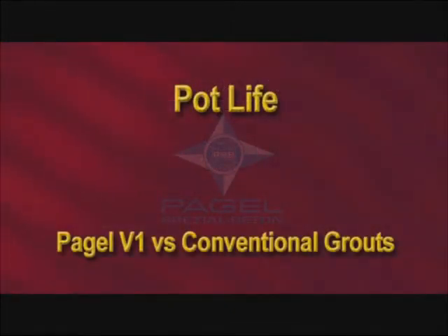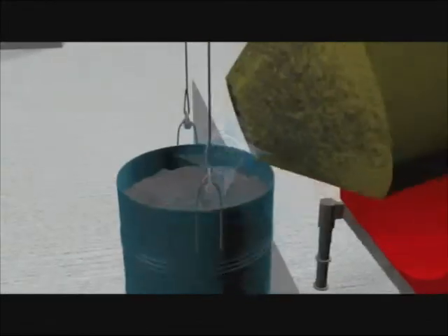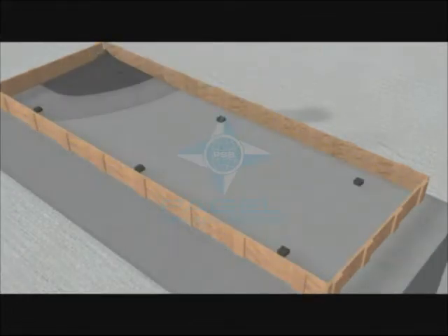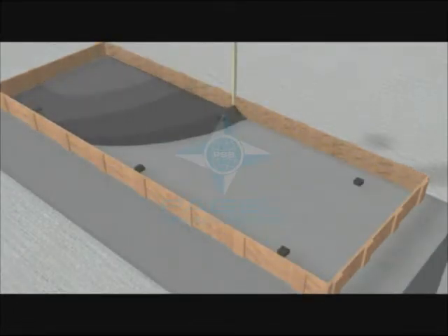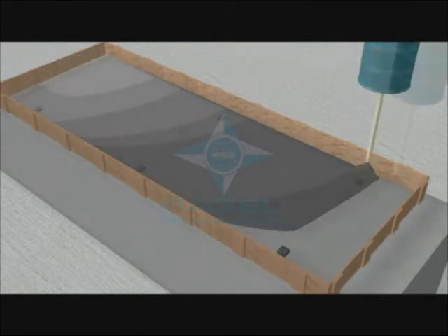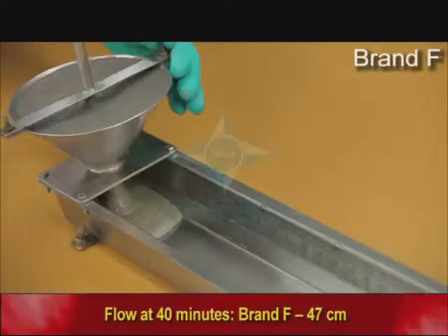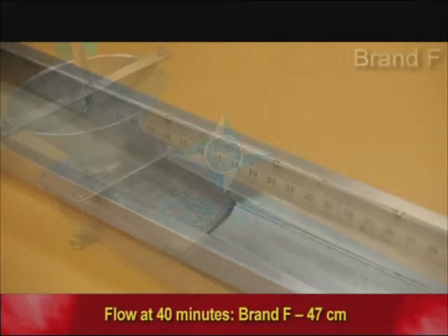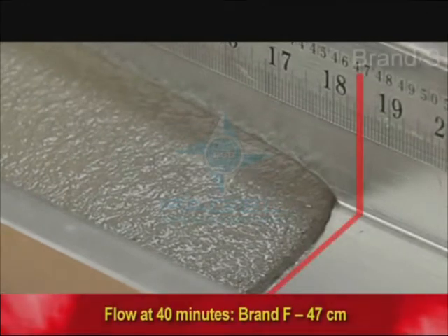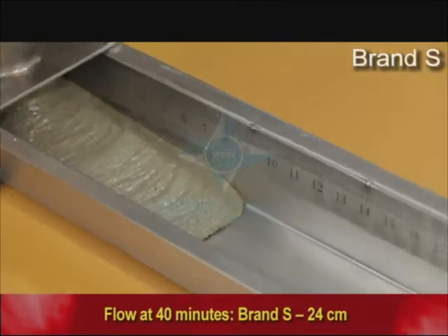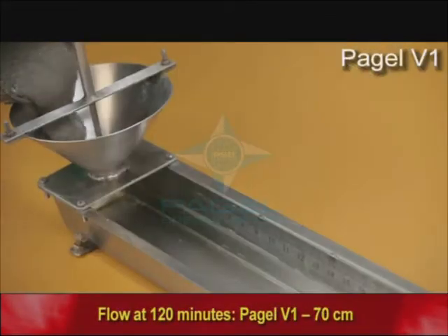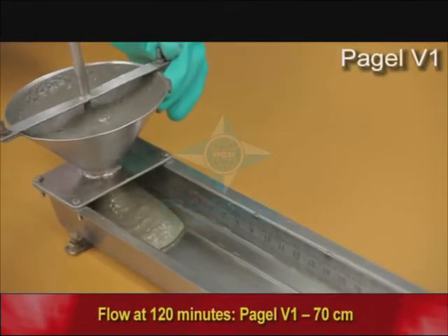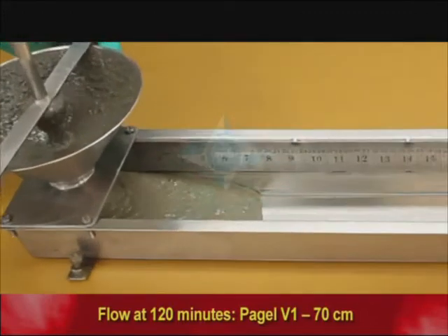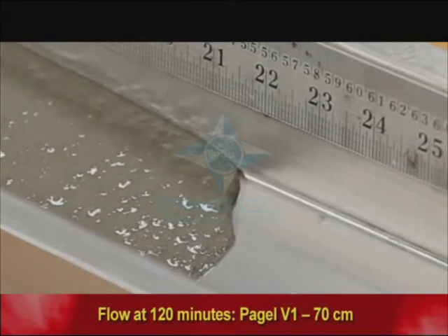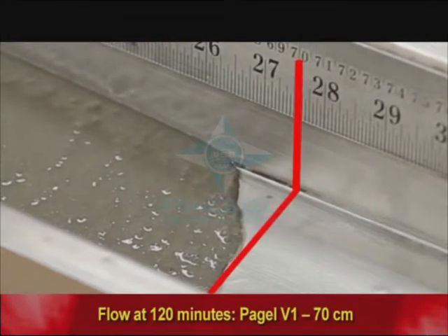Pot life is important for large foundations, where the pour from one end to the other will usually take a long time. With low pot life, each pour will start setting soon. This can lead to cold joints, which can lead to grout failure. After just 40 minutes, Brand F flows only 47 centimeters. Brand S flows a minuscule 24 centimeters. But amazingly, even after 120 minutes, the Pagel V1 grout is still almost unaffected and flows an unbelievable 70 centimeters.